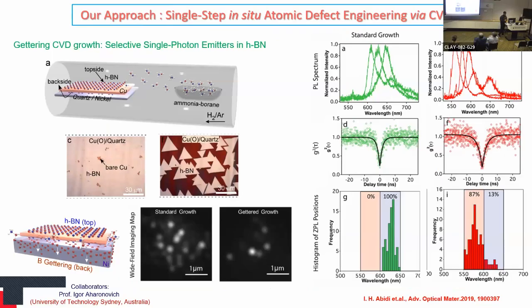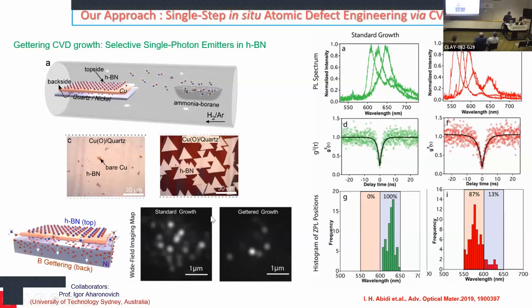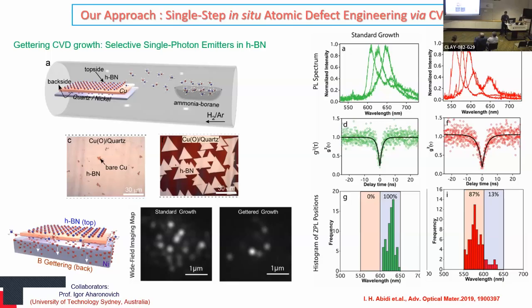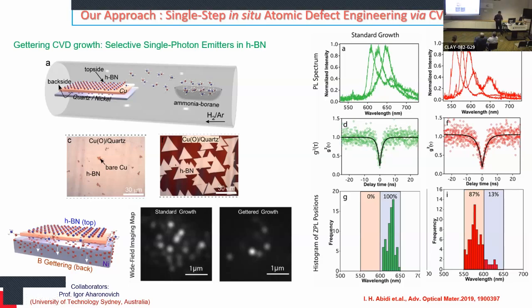The first example: I used the same gettering CVD method to grow boron nitride. Principally the mechanism is the same, because in this case, again, we are using copper foil, and on the copper foil, we grow boron nitride. Once we do this with two different types of substrates, the defects in the boron nitride were changing. Over here, this is the PL emission spectrum image of the boron nitride grown under two different growth conditions. Once we have a gettered growth, in that case, we have fewer quantum emitters, and we can also change the position of the emission based on the defect control in the boron nitride.